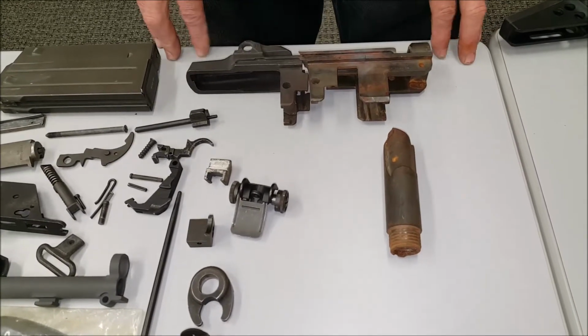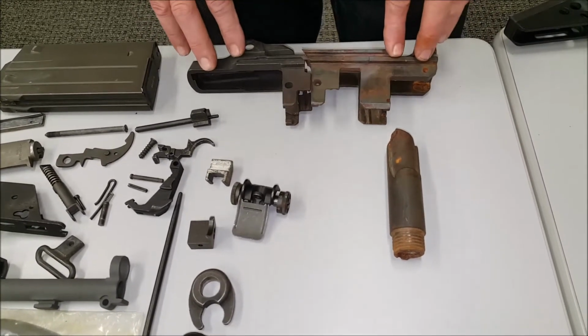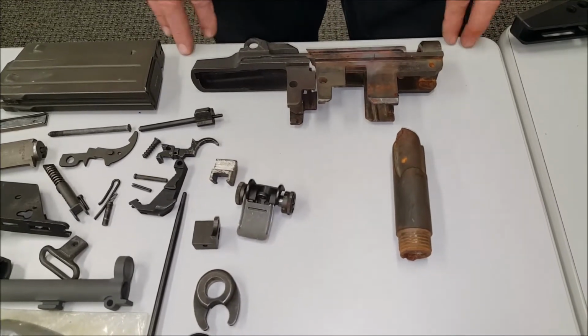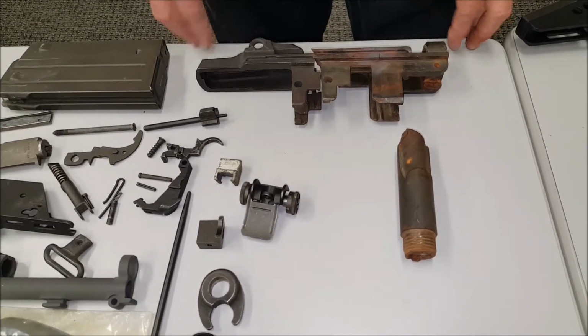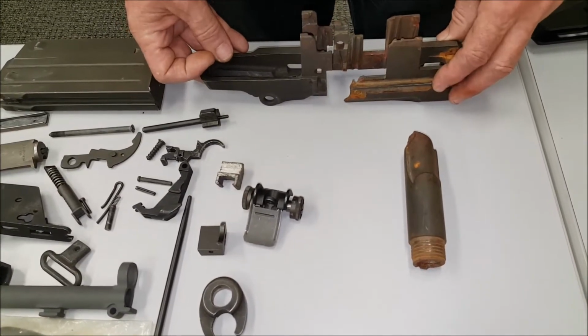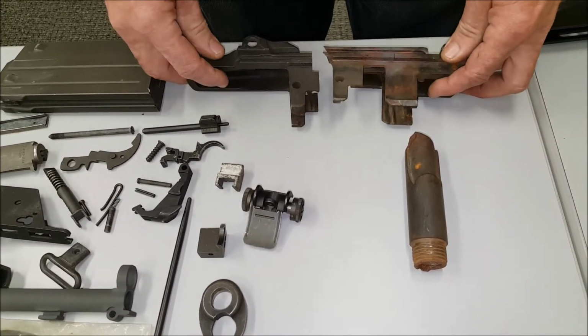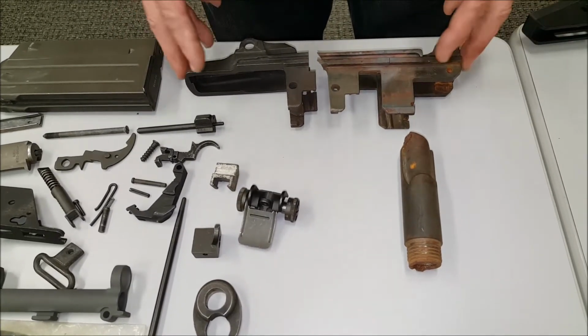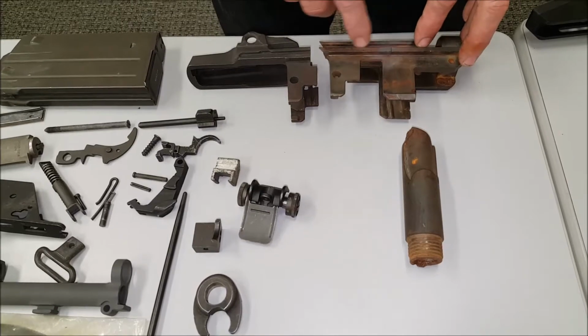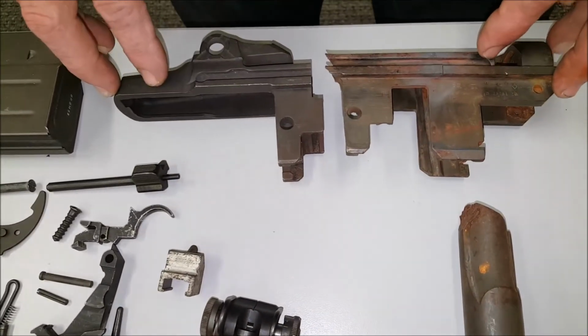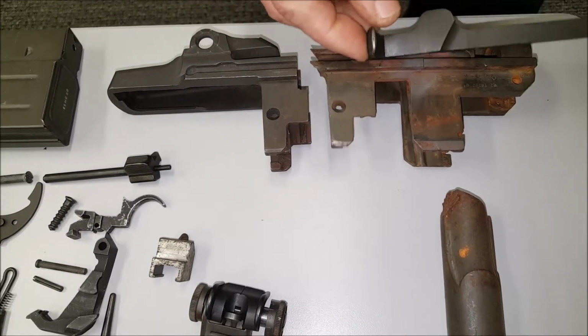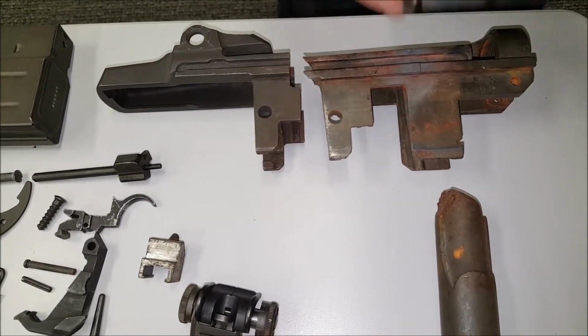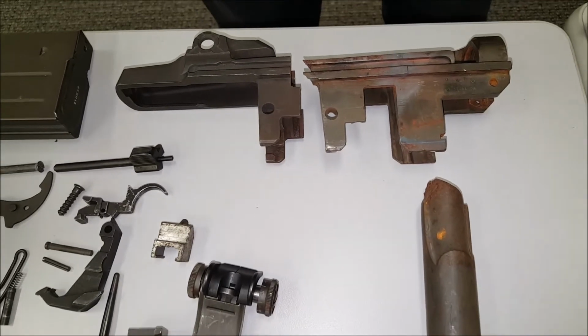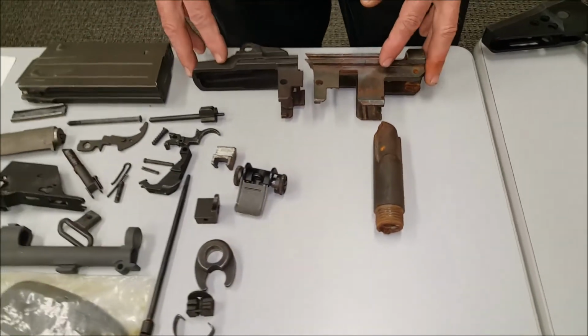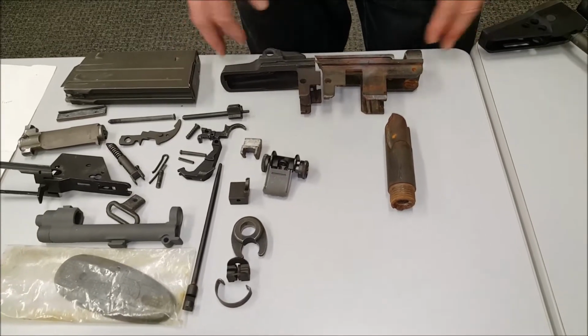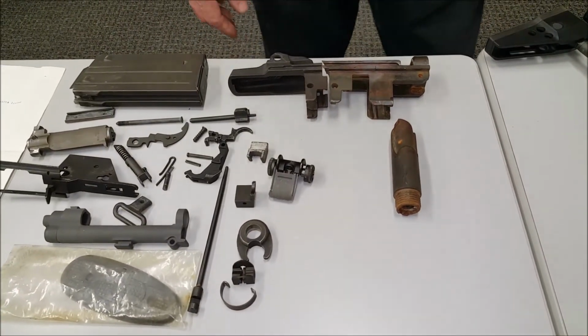If you're going to re-weld a receiver, you need to normalize it or anneal it first, and then do all your work on it, and then reheat treat it to where it comes out with that hardness. You could have too soft a receiver, which will prematurely wear everything, especially on the rail here where the op rod rides. The op rod rides in this rail here, and if it's not hardened properly, it'll wear out where the op rods will pop out while you're shooting it. There's no shortcuts when it comes to re-welding. You can either do it correctly or you can end up with something that's very dangerous.